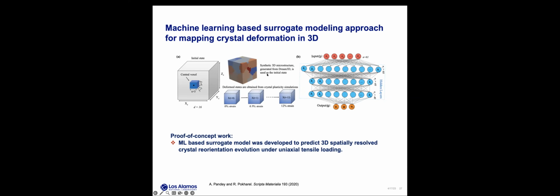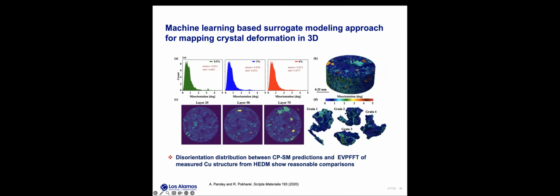So we generated synthetic 3D microstructure data using Dream 3D, and performed a deformation simulation using EVP-FFT, or elastoviscoplastic fast Fourier transform simulations, and those data sets were used for training our neural network model. And once trained on the simulated data, we applied the simulation-trained network to the experimentally measured microstructure data.